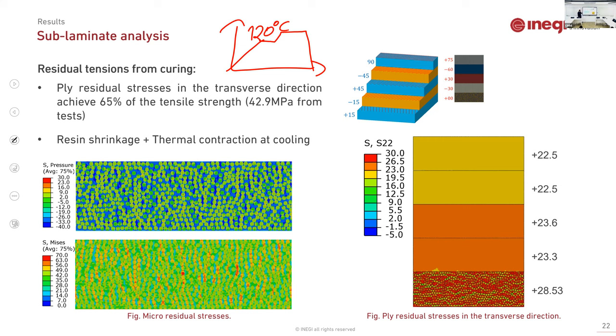If we look at the microscale level, internal micro-residual stresses develop because the fibers and the matrix have different thermal expansion coefficients. Besides that, the resin, which is a thermoset, exhibits a phenomenon called shrinkage, a chemical contraction that tends to reduce the volume of the material. The combination of these two effects develops a distribution of internal stresses to achieve local equilibrium, let's say.